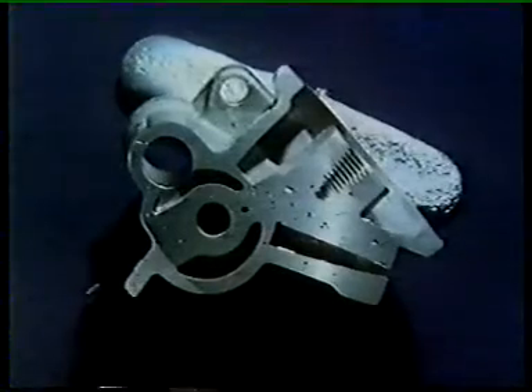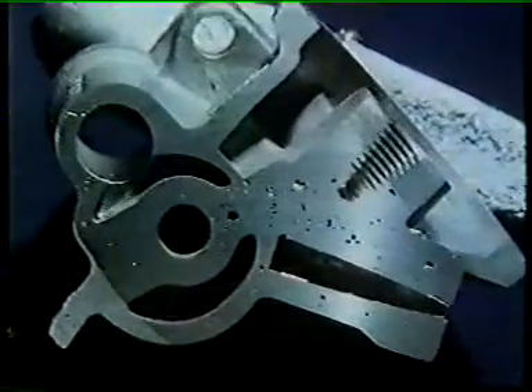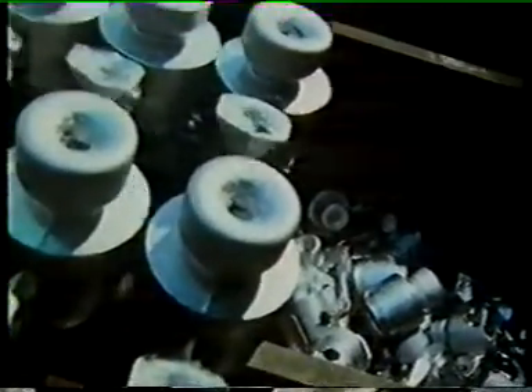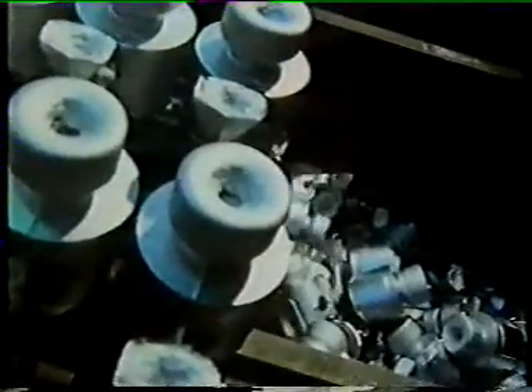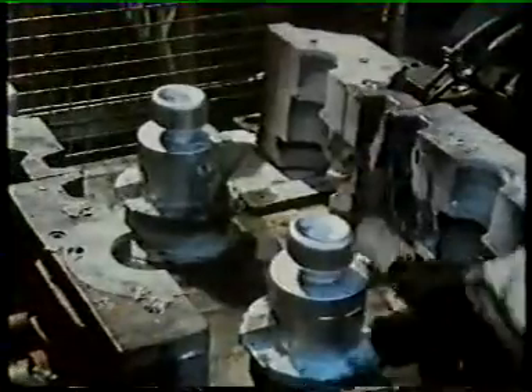A large amount of porosity was discovered in this component during ultrasonic screening. This would weaken the structure, so it was rejected. Strength is given to the casting by age hardening. Pistons are produced from heat-treatable alloys. They are initially gravity die-cast in a similar way to the sumps, but on a smaller scale.